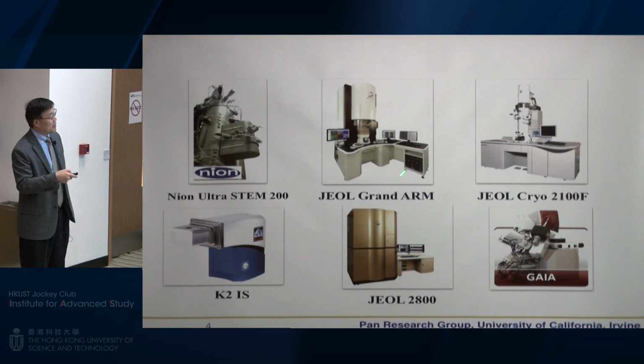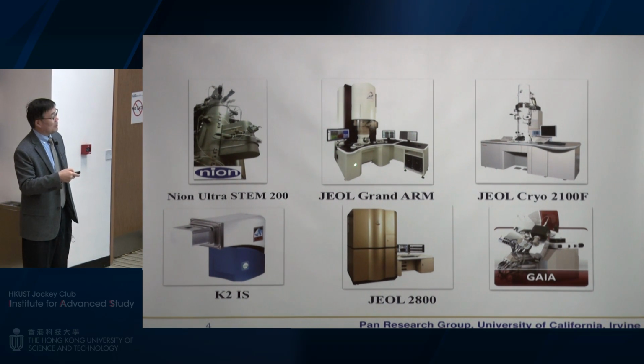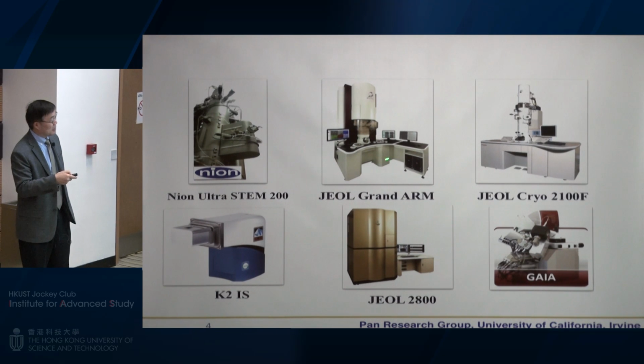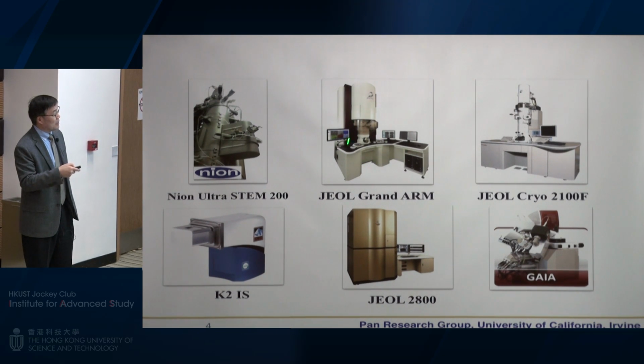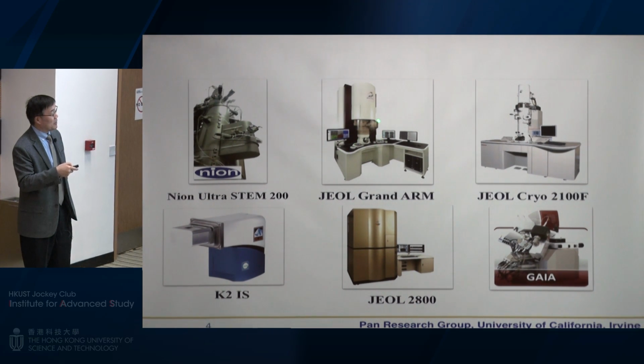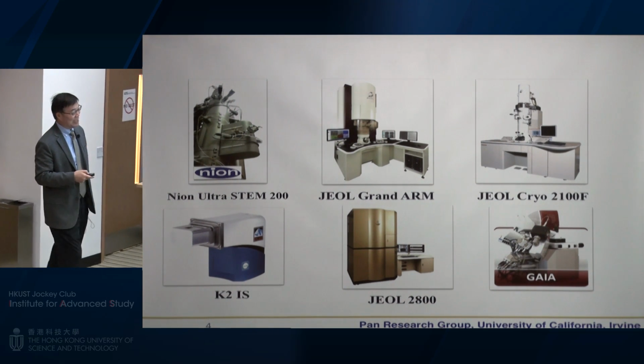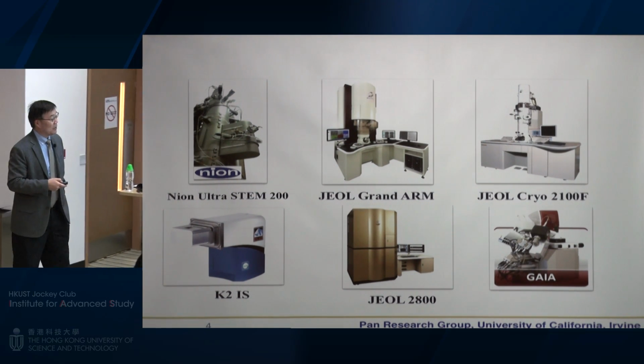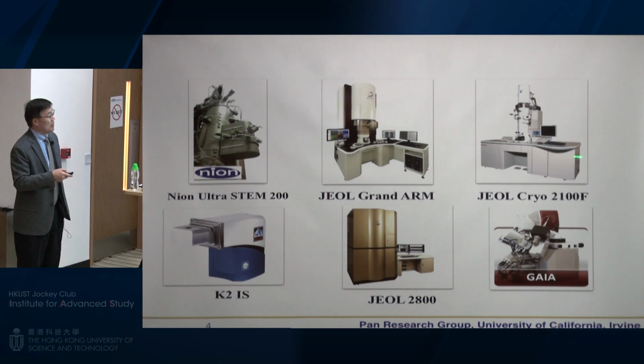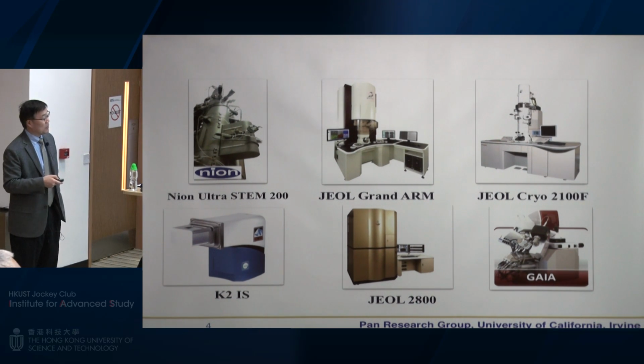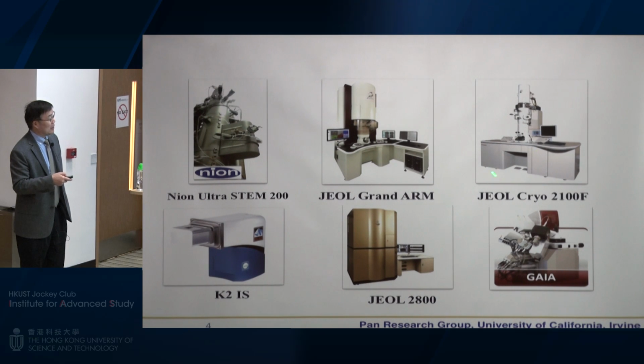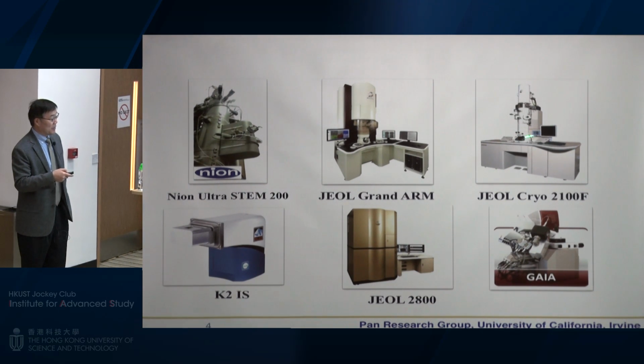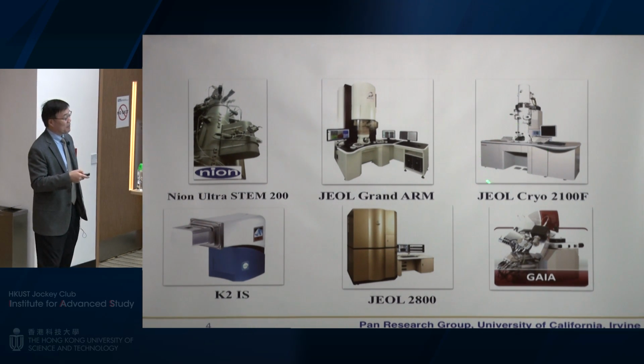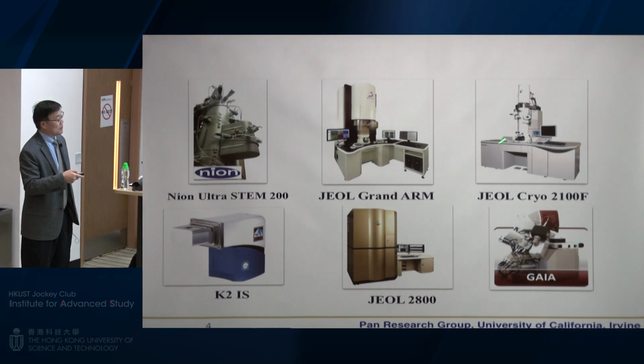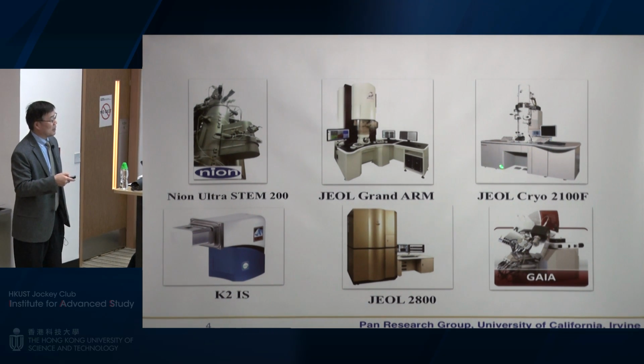And the JEOL most advanced ARM, this 300 kV atomic resolution microscope, with a specially built wide pole piece gap so that you can do a lot of in-situ study even with your customized holder. That is a cryo-TEM for structural biologists, with atomic resolution of 2 angstrom to 2.5 angstrom for structural analysis of biosamples.